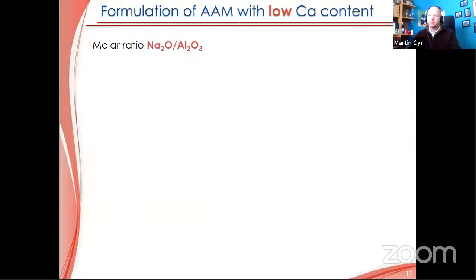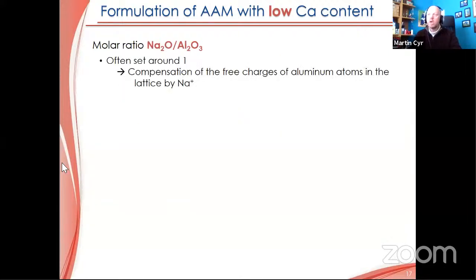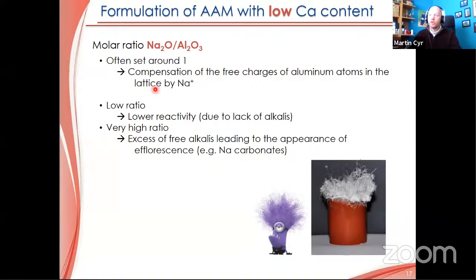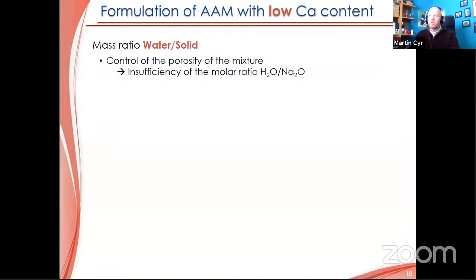What about the others? If we take the sodium over aluminum ratio, usually it is set around 1. It was set earlier. What will happen if we don't use a value around 1? What can be said here is that if we lower this ratio, we can see probably a lower reactivity. We don't have enough alkalis inside to make the reaction strong enough. And on the other side, if we use much more than a value of one, we probably will have a lot of free alkalis, and we will have the appearance of a lot of efflorescence, as you can see here. So you have to manage also this ratio, and that's true that a value around one is usually acceptable for this kind of material.